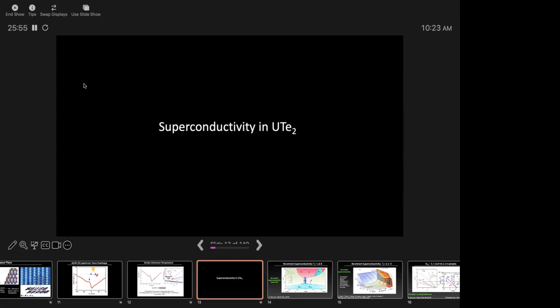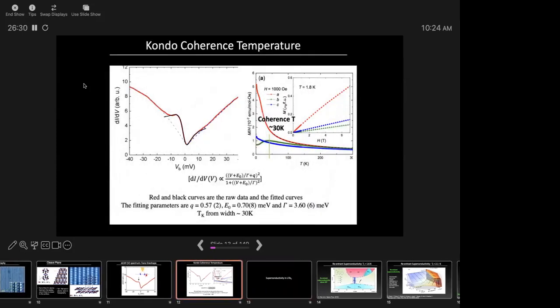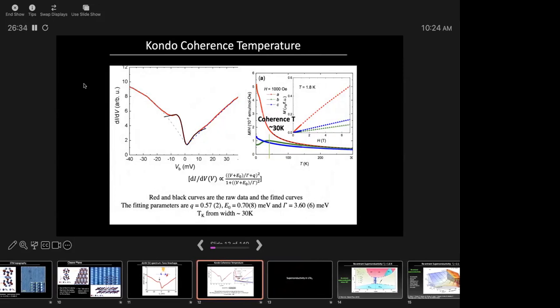Well, there's spin fluctuations. So basically, if you really had fully screened spins and you were at very low magnetic fields, Kondo shouldn't get affected by low magnetic fields. You shouldn't see anything. But in this material, it behaves like there are spinful objects at low temperatures. Even from muSR, you can see there's spinful objects at low temperatures. So there's got to be partial screening. No, I'm not saying they're ordered. It's an Ising-like system. That's Van Vleck magnetism. I'm not saying they're ordered, they're still paramagnetic, but I don't believe they're fully screened.